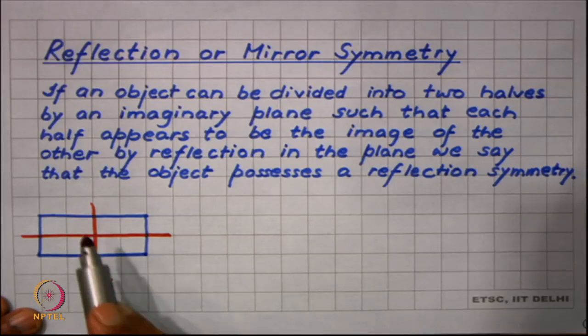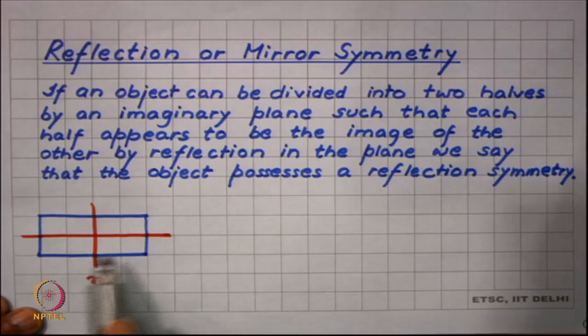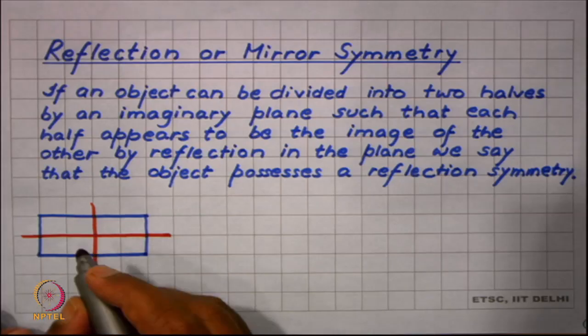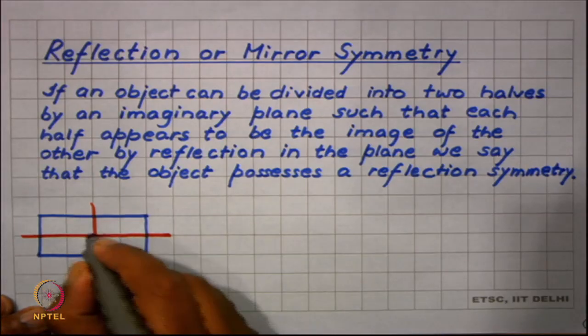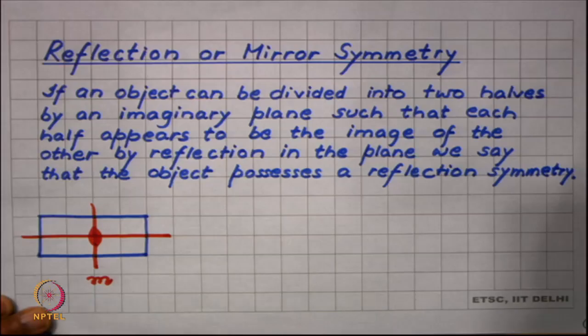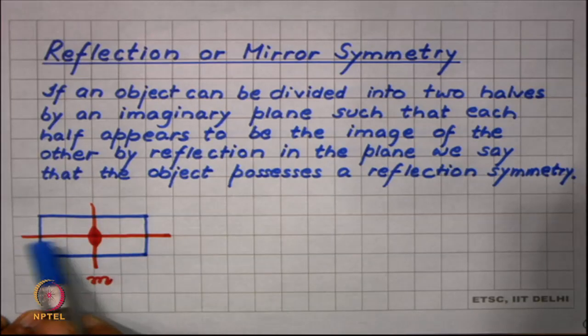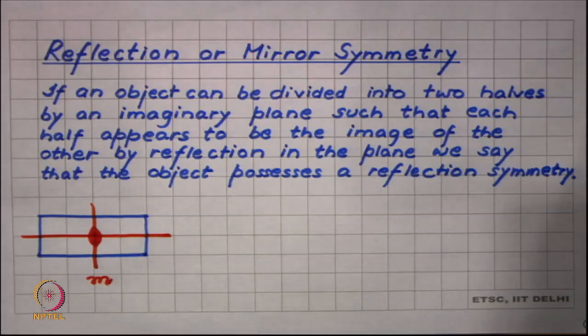In the symmetry definition, the mirror is always a two-way mirror. So, the left is reflected into right and right is reflected into left. We also saw when we were discussing the rotational symmetry of this rectangle that it has a two-fold rotational axis at the center. So, we add that. This is not an accident. This is a general rule of symmetry, that whenever two orthogonal mirrors intersect, the line of intersection is a two-fold axis. So, all these symmetries are the point symmetries of a rectangle.